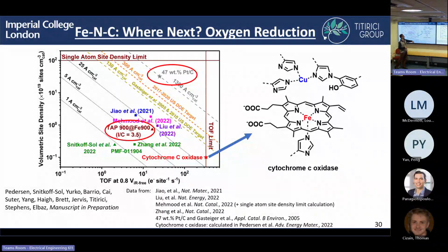active site. If you again go back to biology, you see that the most efficient enzyme for oxygen reduction is cytochrome C oxidase, and this can have a turnover frequency an order of magnitude greater than what we currently have. So we either need to increase the site density or develop a new type of active site, or ideally do both and also make it stable. So there's still more work to do for PhD students, fortunately.